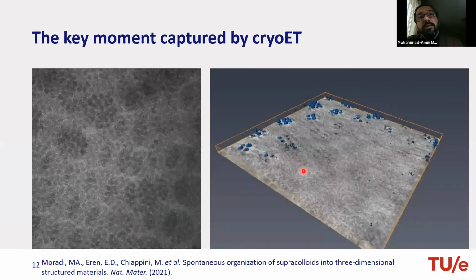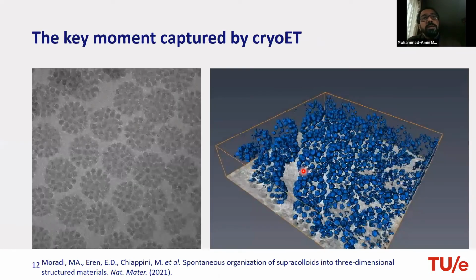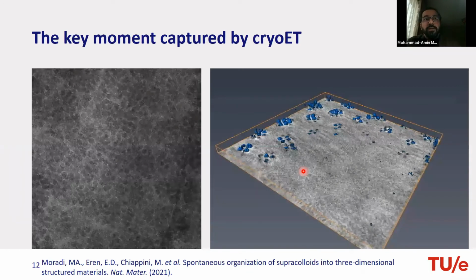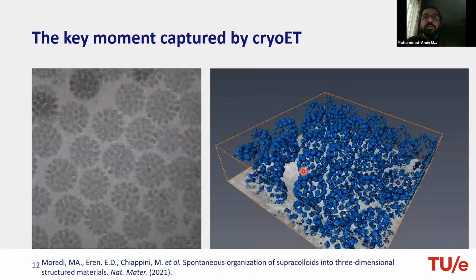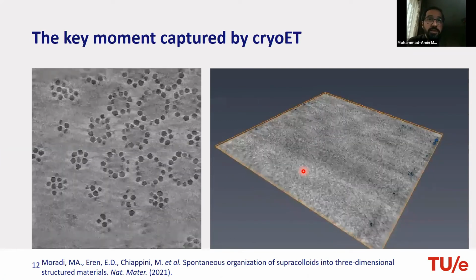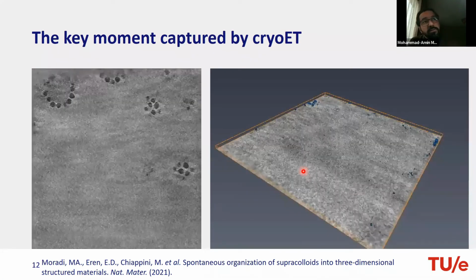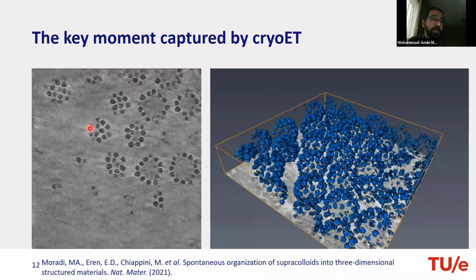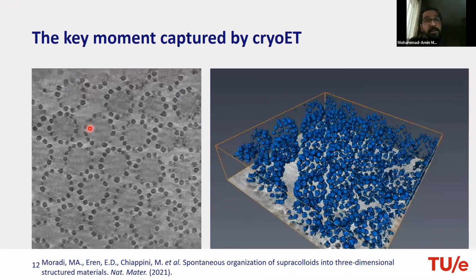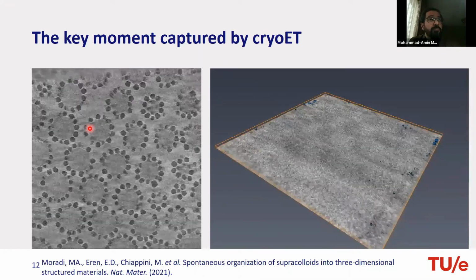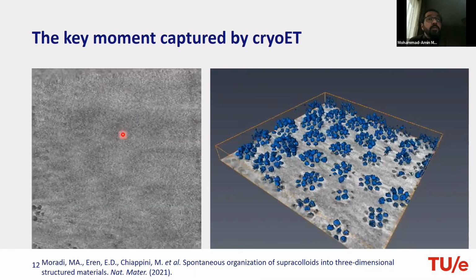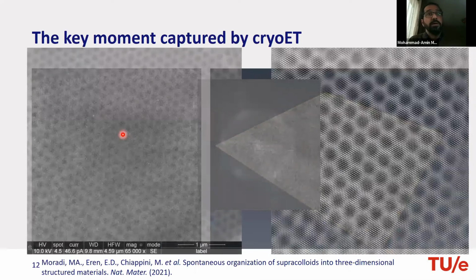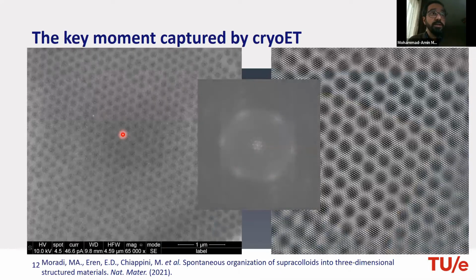But talking about cryogenic electron microscopy, I would like to mention a very special moment in this project where we succeeded to capture the particles very closely. I mean, after adjusting the repulsion interaction, but still not contacting, or let's say not forming a cluster, which was actually from a sample that later on resulted in this beautifully ordered material.